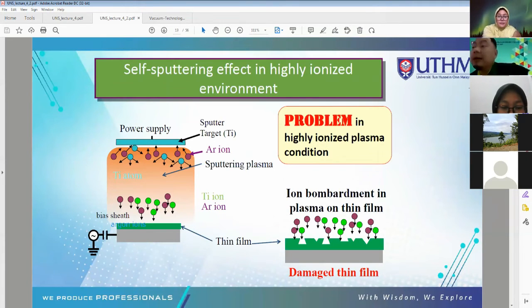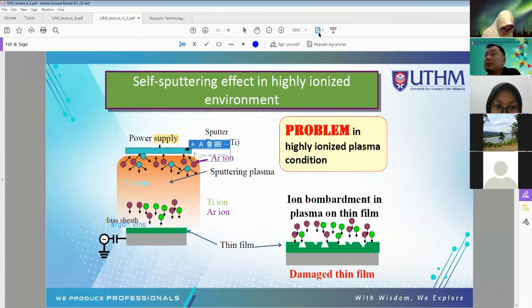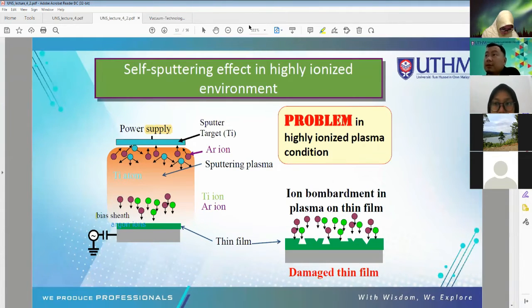This is one project that we did. We studied the self-sputtering effect inside the plasma. Inside this plasma we have our target. We also have the atoms and ions that hit the target. In this case, we use titanium as the target source, and the ion will hit the titanium and release the titanium atom.